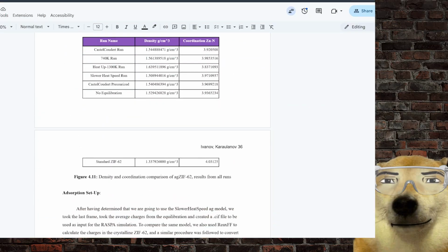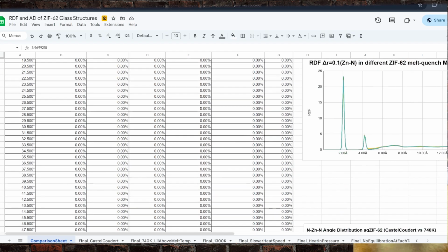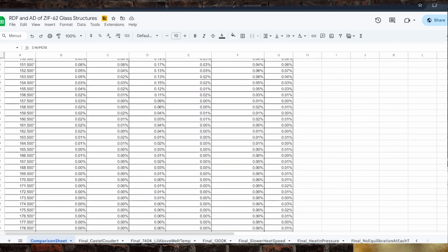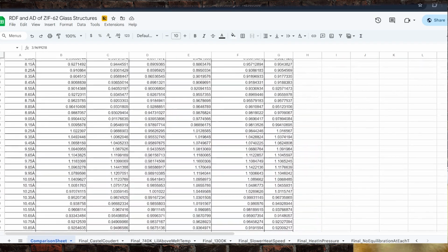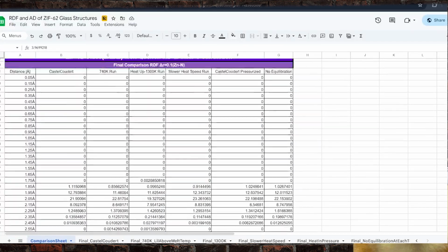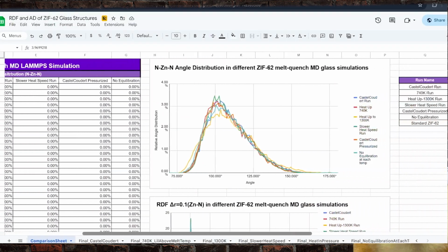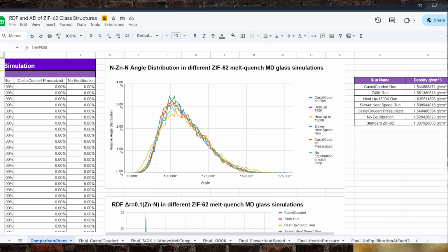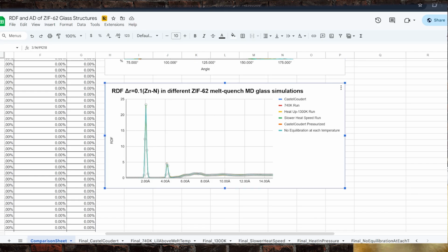For a deeper understanding, we advise you to read the section of the paper, but in general we found this. A. Equilibration at every 100 Kelvin is a must. Without it, the structure becomes abysmal. B. Overheating must be prevented in all cases, as it performed the worst out of all trials. C. More time at molten state also resulted in greater angular dispersions. D. Lower heating speed meant a higher retention of coordination and less dispersed angles, and a better overall structure. And E. Pressure has little to no effect on AD and RDF wise, but retains higher coordination.